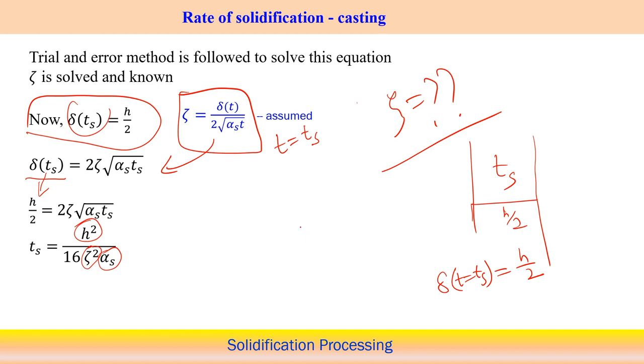Then once we use this expression, delta t by twice, corresponding to ts, at t equal to ts delta is h by 2, so it reaches half of the thickness. When we make this equal, from there we find that ts, the solidification time, depends on h square by 16 zeta square into alpha s. So more or less it depends on this zeta value, and there might not be much variation with changing other dimensions, but it depends more strongly on the thickness of the slab which you are supposed to cast in this process. So this is the way to estimate the solidification time for this particular casting process.